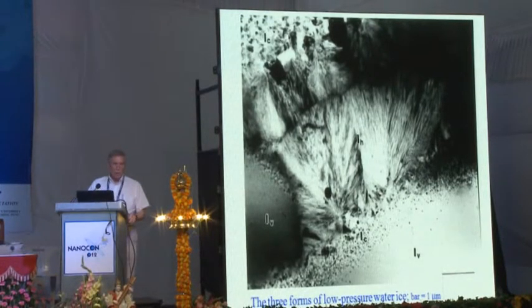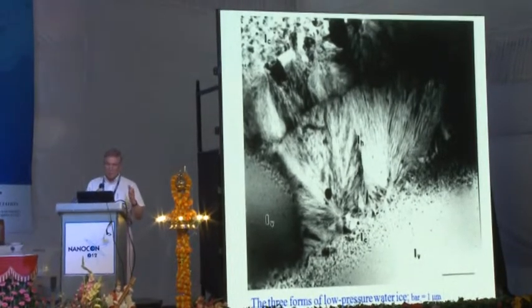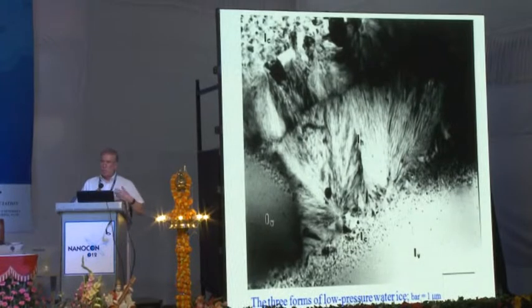But what we would like to do is cool so fast that the specimen does not crystallize. We want to make a supercooled water, a glass. And this is, you see it on the screen, in areas that are denoted IV, vitreous ice. So we want to make it a glass. This is not a real solid. This is a liquid of very low vapor pressure and very high viscosity, and it preserves the original nanostructure of